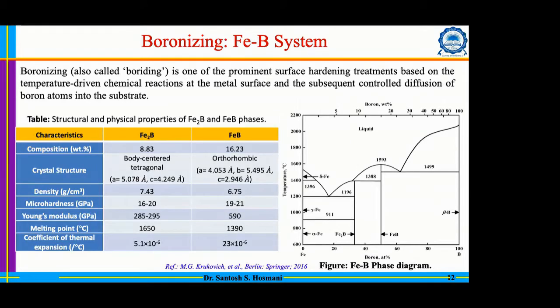Now, what are the properties which we need to understand? Because there is always a question whether it is better to have a single-phase boride layer, or whether we can have a two-phase boride layer. To answer that, you need to understand the physical properties associated with this. With respect to composition, whenever the boron content in steel exceeds roughly 9 weight%, the Fe2B phase will form. And whenever the concentration of boron exceeds about 16 weight%, the FeB layer will form.